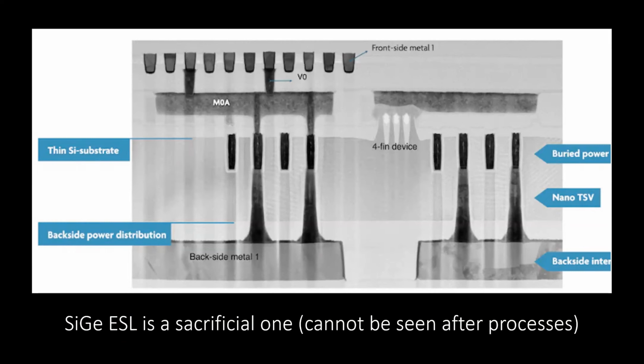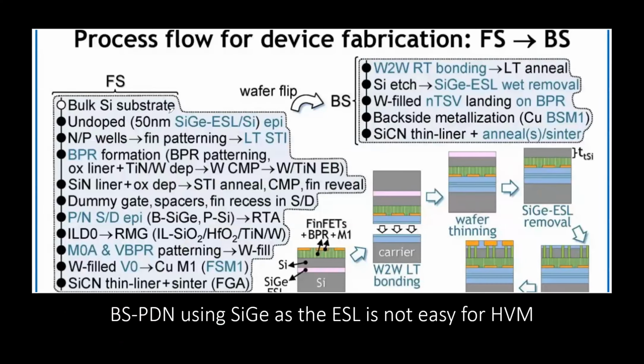And let's review its flow a little bit. You can see that the silicon, this is the bulk substrate. They bought it from MEMC or somebody, right? Now they're going to do an epi SiGe, and that's your stop layer. And then you grow this, and then you grow silicon on top of it. So that's an epi done by probably an ASM tool, and ASM is pretty good at doing this, right? And then you have a well, and then fin patterning. We can talk about this later. All these are prop, and then the low temperature STI.